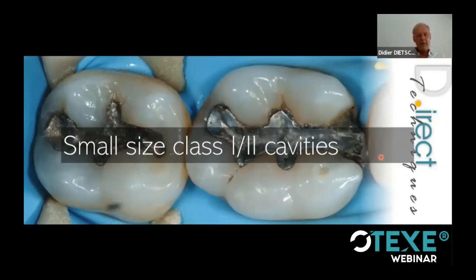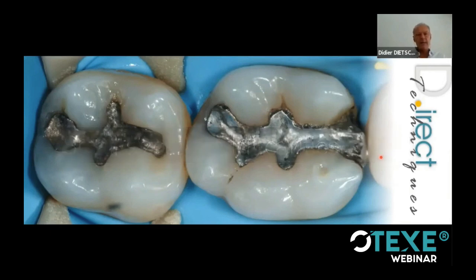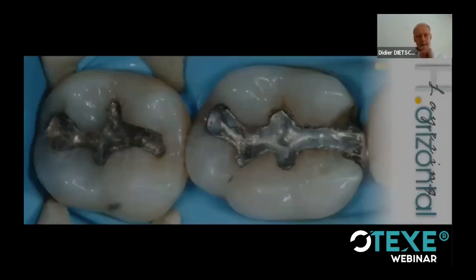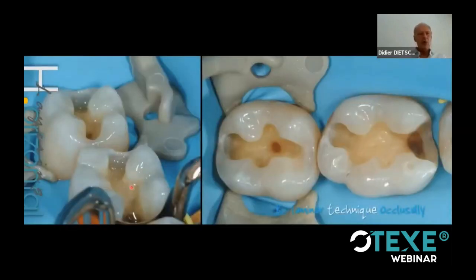First, for a small size class 1 and 2 cavity. What is small size? It means that from a buccolingual dimension, the cavity is less than 1/3 of the buccolingual dimension. And when we open the cavity, you see that really the volume of the restoration is relatively small. And in the proximal, what is also for me the condition for a successful application of those techniques is to get plenty of enamel. We have nice, thick proximal enamel. We could make a nice bevel on the cervical, which is also needed to get a perfect adaptation in this area.